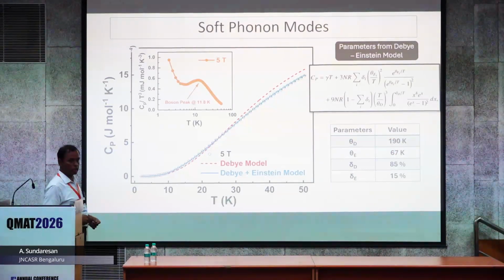Most importantly, we plotted C by T cube versus T, and you can see at 5 Tesla, which is in the normal state, a boson peak, further supporting that you have strong coupling superconductivity coming from lattice spin electron phonon coupling.